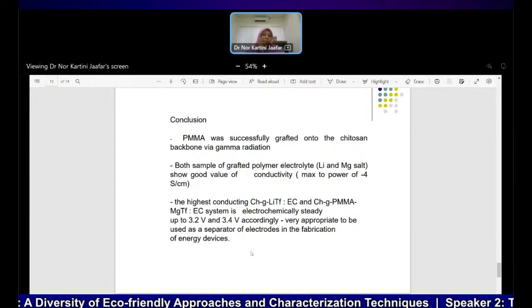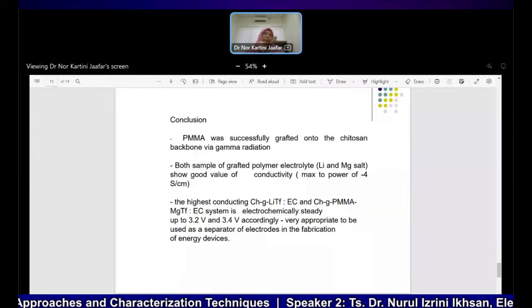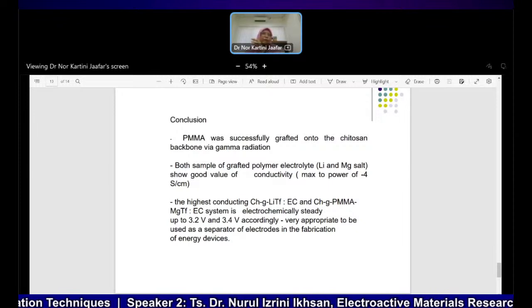Actually, for the lithium system, I already tried to fabricate it with a supercapacitor. It showed the compatibility of the polymer with the electrode, using just carbon electrode. But to have very good cyclability and very good capacitance of the supercapacitor, we must adjust the electrode also.